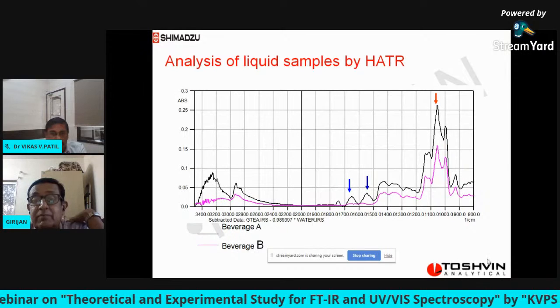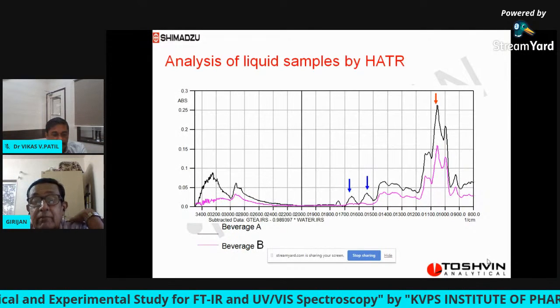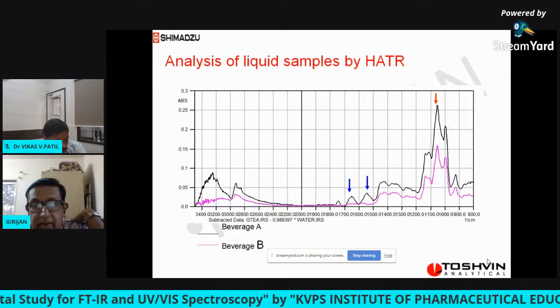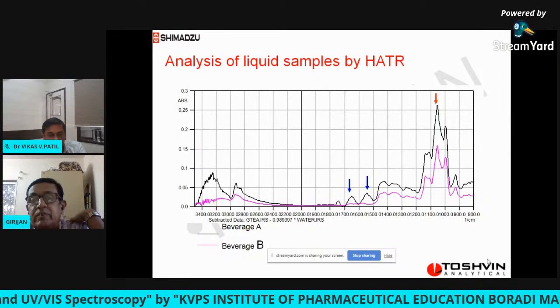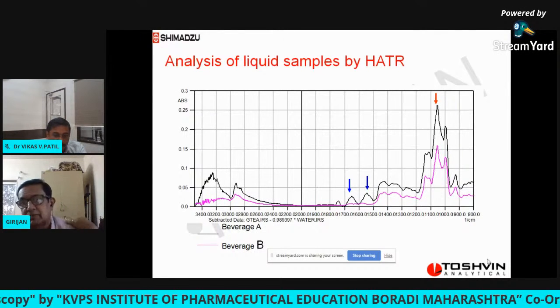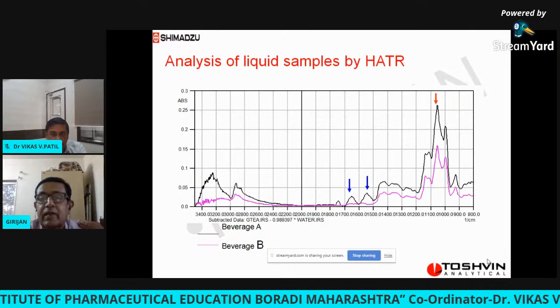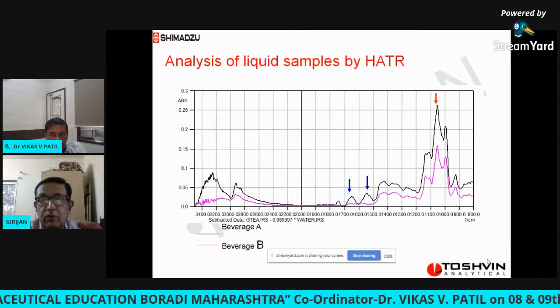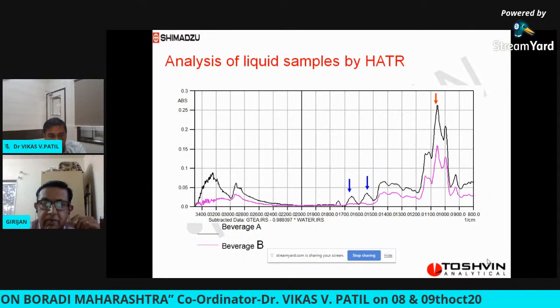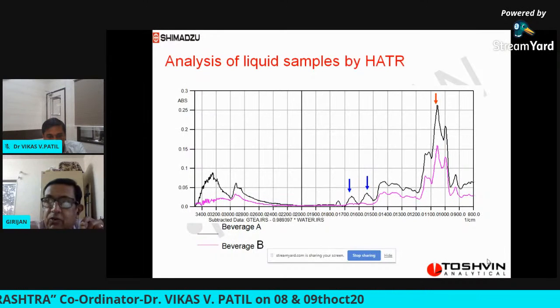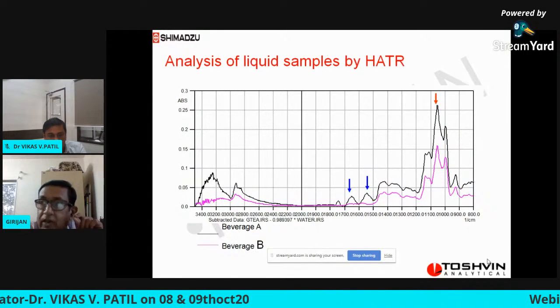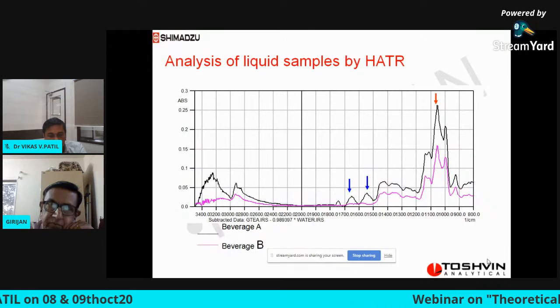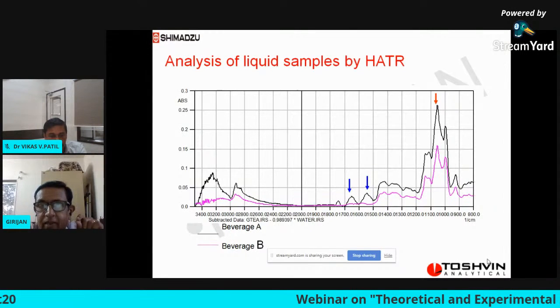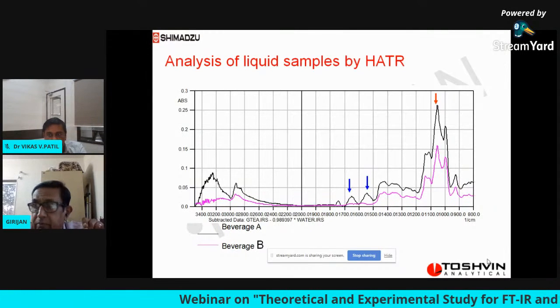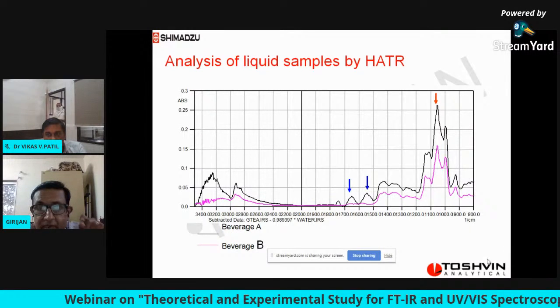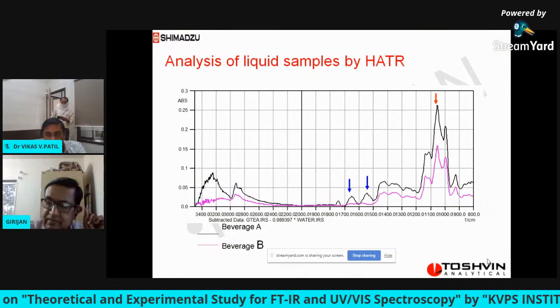Here you can see the striking differences in the absorption bands in beverage A and beverage B. There are 2 or 3 separate absorption bands appearing in beverage A which are not present in beverage B. And you can see the difference. Clearly, there are a lot of differences in the spectrum. So that means both the spectra are totally different, so you are able to differentiate between these two. And these are recorded by HATR without any sample preparation, just keeping the sample on the crystal and recording the spectrum, as easy as that.